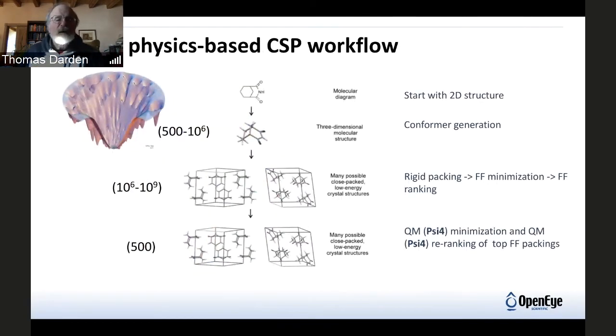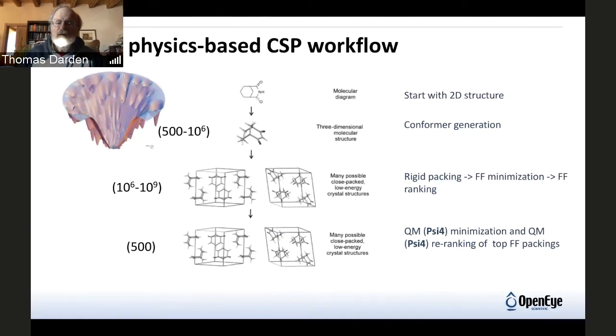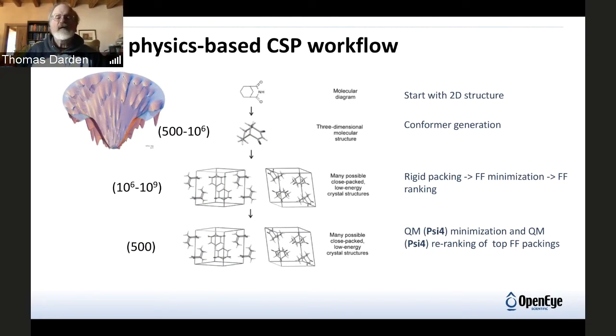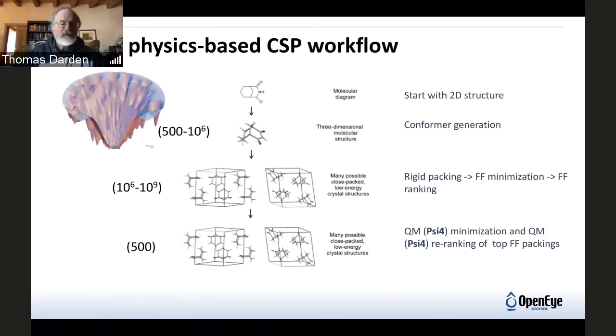In more detail, you start with a 2D structure and generate conformers — usually about 500, maybe 1,000 or a couple thousand. With 11 rotatable bonds, this explodes exponentially, and if there are co-crystals, solvates, et cetera, the conformational problem explodes further. For each conformation and a series of space groups you search through, you generate maybe 1,000 random packings per conformer per space group. This is a huge number of packings, so you need cheap methods to get down to something on the order of 100 to 500 structures for minimization and re-ranking.